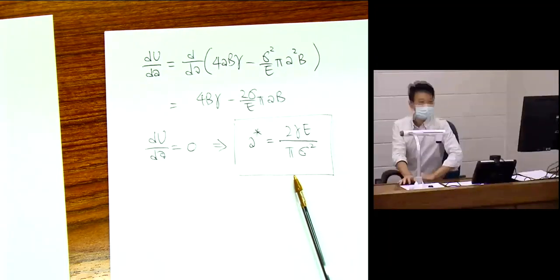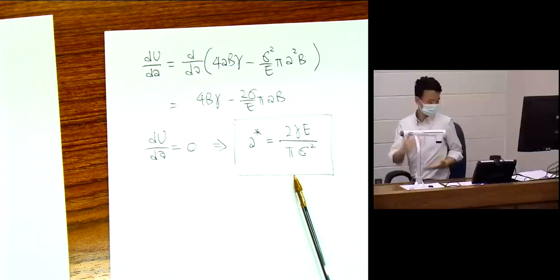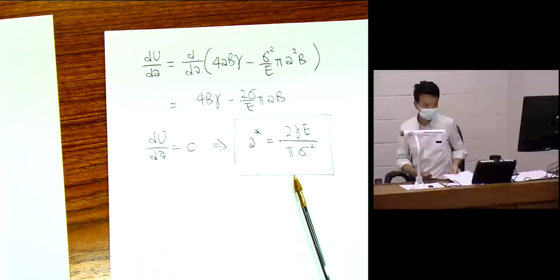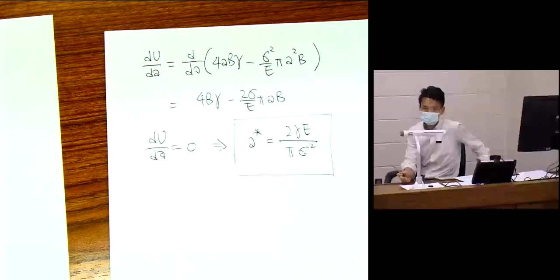So this is, again, let's take a look at this, right? We can calculate the A star given the conditions of the experiment that we are doing, okay? Because over here, elastic modulus and the surface energy are material properties, right? If you take a piece of material, you look it up in tables, you know these numbers.